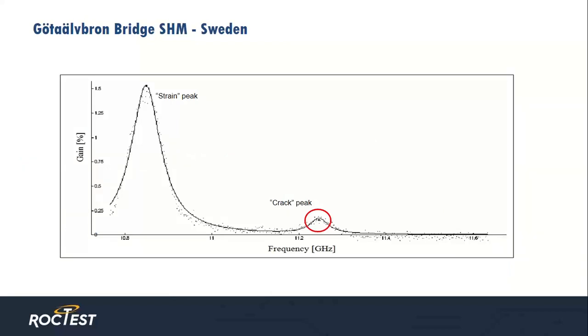Okay, in the plot we see here on the screen, the main peak represents the average stress over the length of about a meter. The secondary peak here called out in red represents a variation in local stress caused by a crack. And this secondary peak is caused by the delamination of the smart tape itself. As the coating starts to delaminate, the strain changes, and to the effect that we can see this secondary strain peak to localize cracks. So based on this technology, we can detect cracks down to about a half millimeter over the length of 100 millimeters.